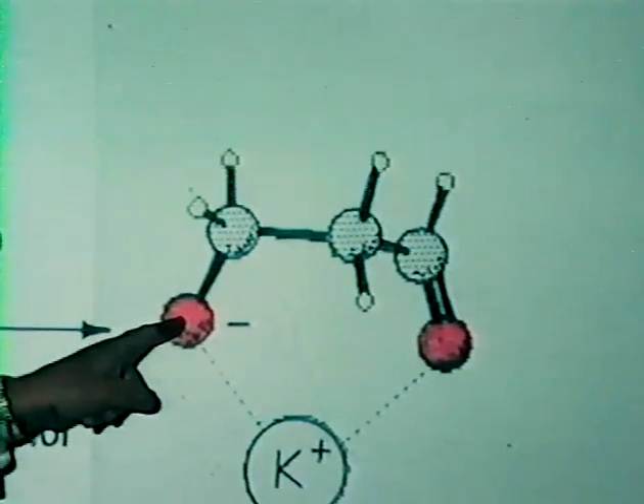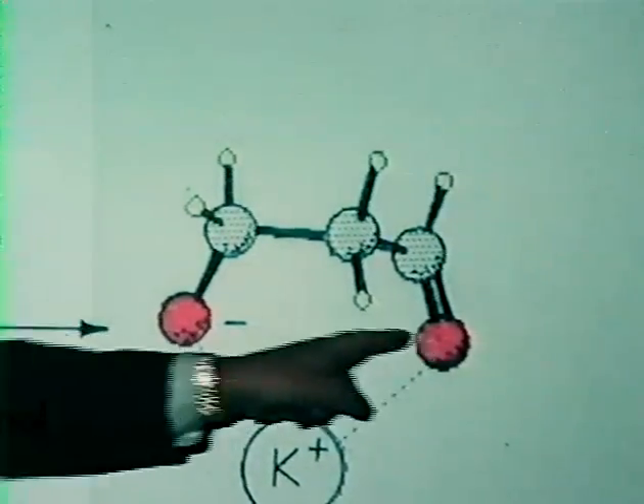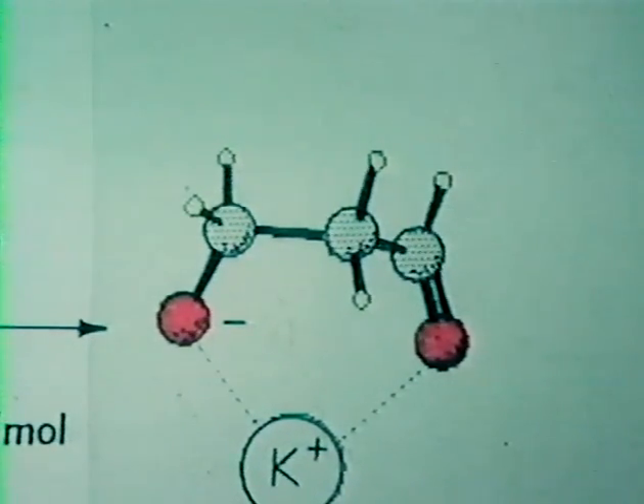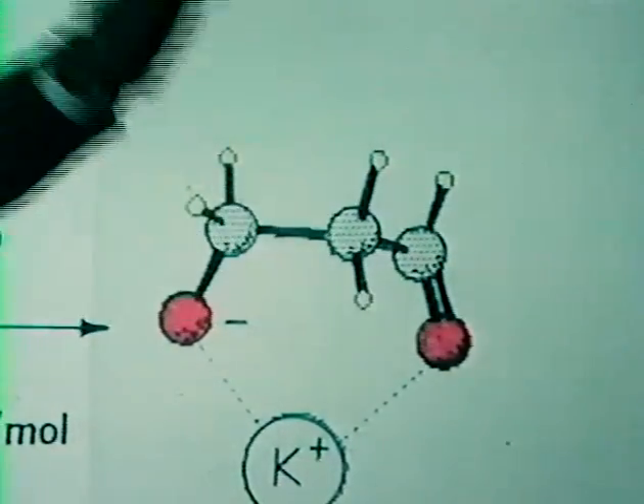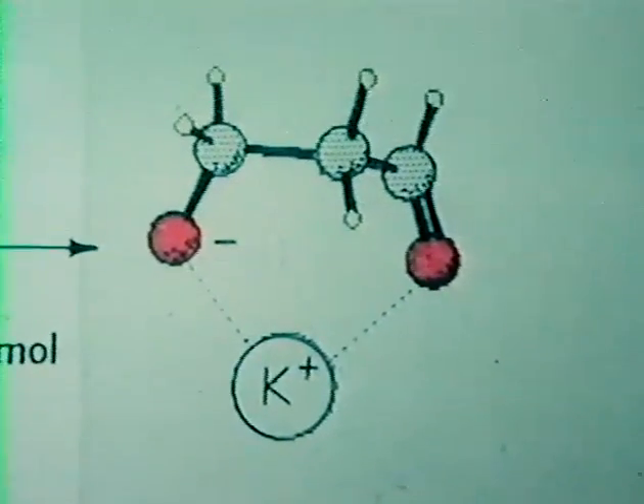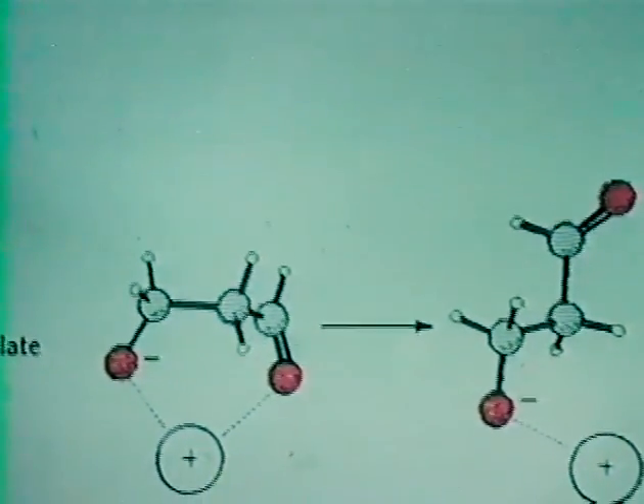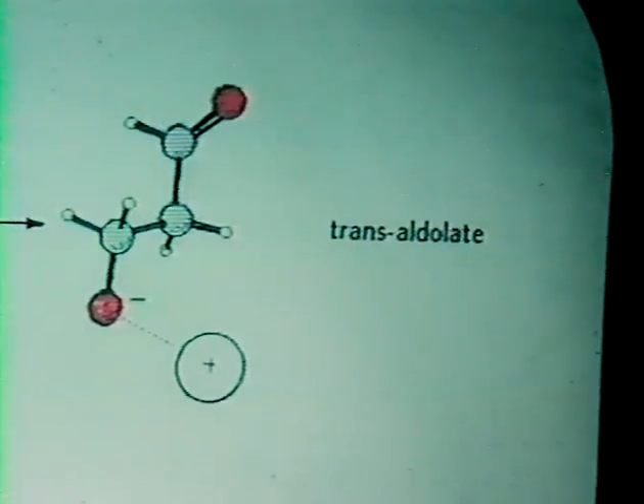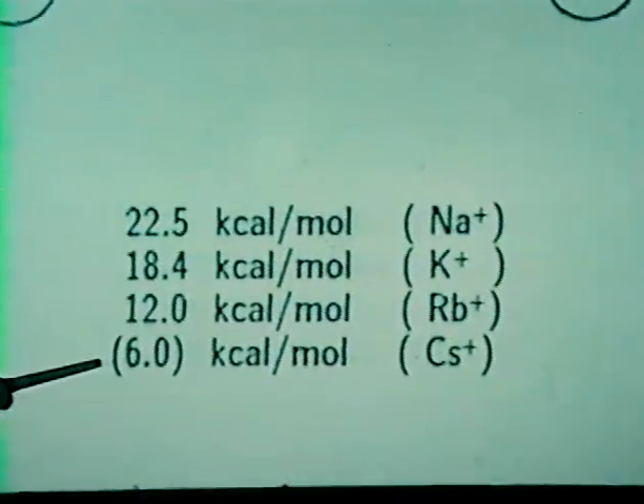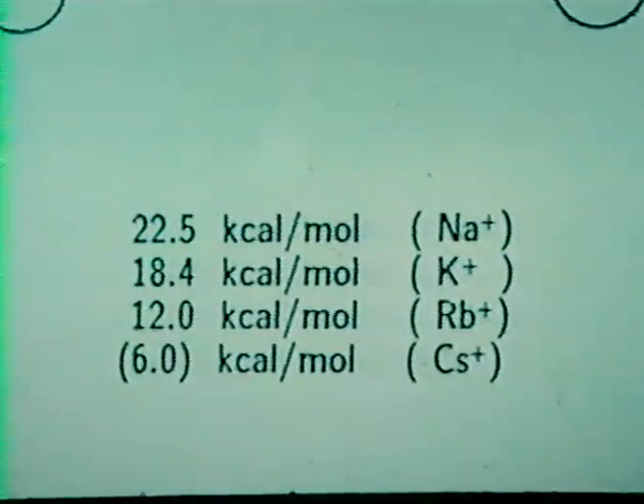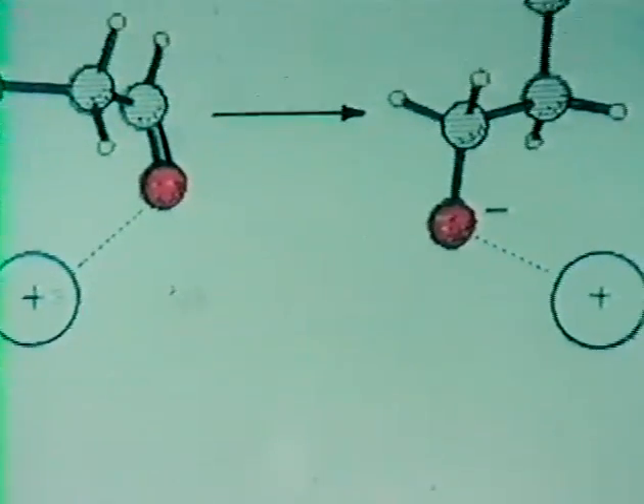This alkoxide group is bonded to the alkali ion more strongly than the keto group. Incidentally, these are results of calculations with optimized geometry and all that stuff. Now we're studying how much energy it will cost, depending on the nature of this alkali cation, to move this group into the trans configuration, because the trans configuration will render the CO group, the carbonyl, susceptible to hydrogenation to CH3 over the copper zinc oxide hydrogenation component of the catalyst. So we studied theoretically this reaction, and interestingly, what was found is that the reaction costs you an awful lot more energy if the cations are small and an awful lot less energy if they are large. In other words, this isomerization is easiest for the heavy alkali ions, such as cesium, which is our co-catalyst.